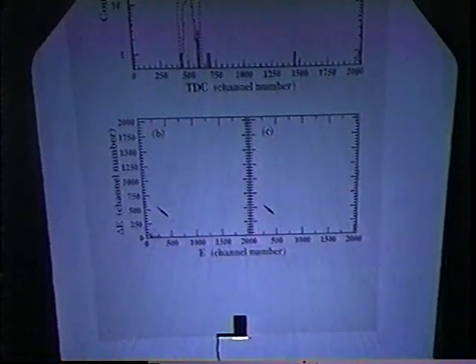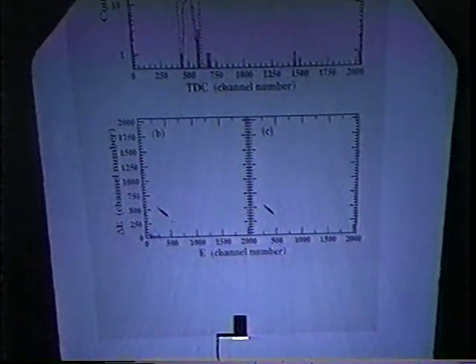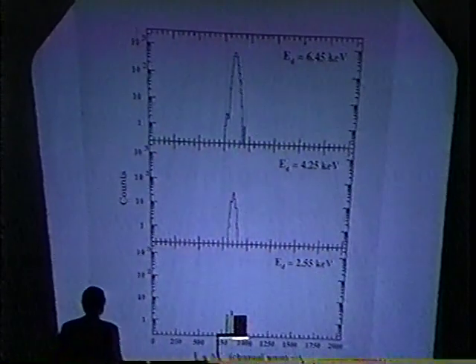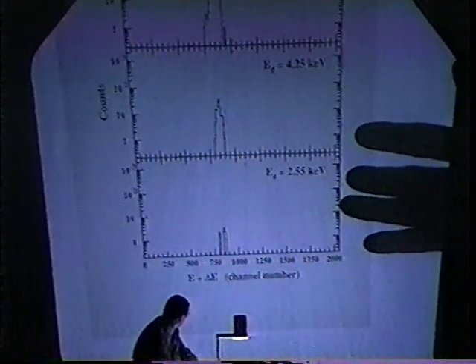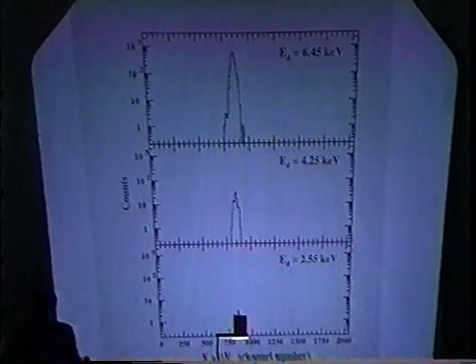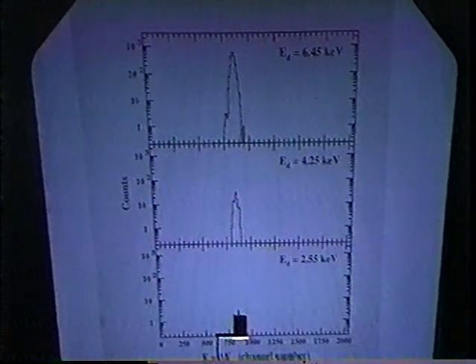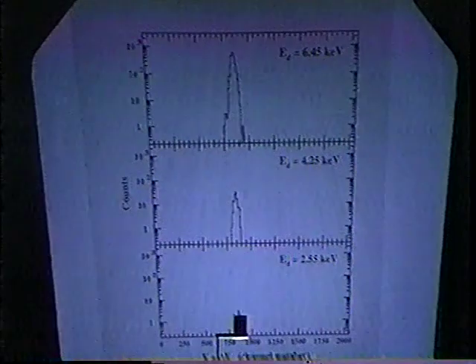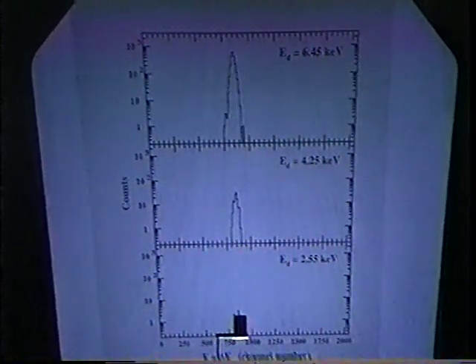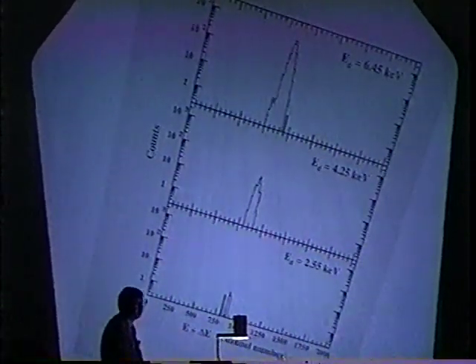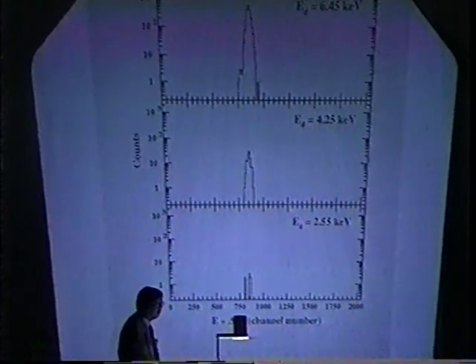And in this case, without any selection, you see the noises around here. But if you put the gate on the top TDC spectrum, the noise are all gone, and only the proton signal, or the real signal, can remain. And this is the spectrum projected on the E plus delta E. So only one peak can be recognized, and no background at all, because we selected the time correlation between delta E and E. Therefore, we could go down. I don't know, maybe if we do the measurement for 1 month, then we might go down 1.5 keV or so. But anyway, up to now, we have data down to 2.55 keV.